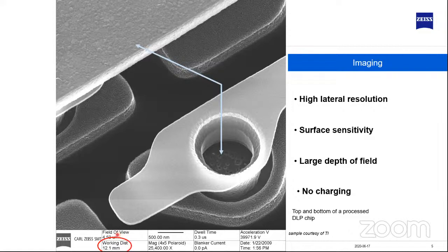So in an SEM, you would go to working distances like 2 millimeter, 1 millimeter if you want to go for the highest resolution. In this instrument here, we can afford to go to very long working distances. And that's a consequence of the fact that the ions have a higher mass and a shorter wavelength than electrons. Therefore, we're not diffraction limited, and therefore we can use very small apertures, and that actually results in a beam with a very small convergence angle, and that results in this very, very large depth of field. It's about a factor of 10 bigger compared to a field emission SEM.